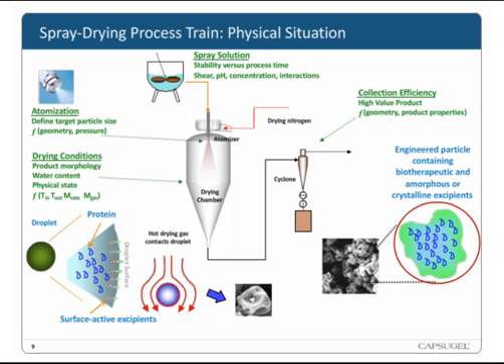So we pump that spray solution through an atomizer. The atomizer defines the droplet size, which in conjunction with the solids in the spray solution will tell you what your particle size is. And then in the dryer, the extent and the rate at which we evaporate the solvent can become important when we think about things like spray drying proteins, where the protein oftentimes will like to go to the air-liquid interface, and we may need to compete that off the surface with a surfactant or other type of amphiphilic molecule.